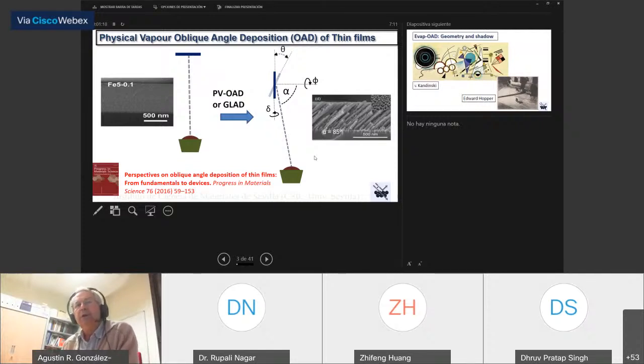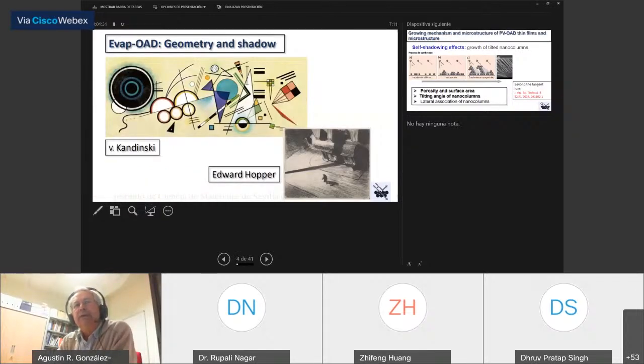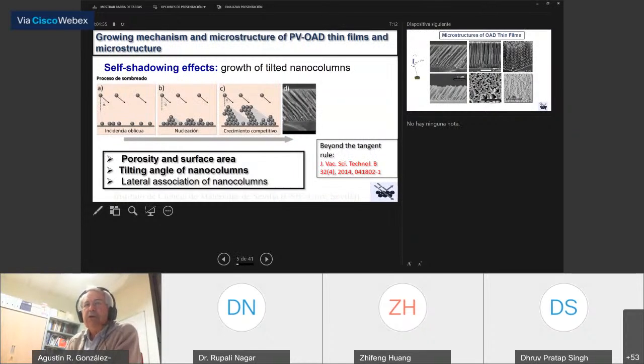So if I have to stress two basic principles that control this growing mode, I would consider that they are controlled basically by two physical principles. On the one hand, geometry, as happens in this very nice painting by Kandinsky, and shadow, as in this very nice picture by Edward Hopper. Taking into account just these two basic principles of controlling the growth process, what we obtain is this very nice nanocolumnar structure where we can control the porosity, the tilting angle, and also perhaps the lateral association of nanocolumns.